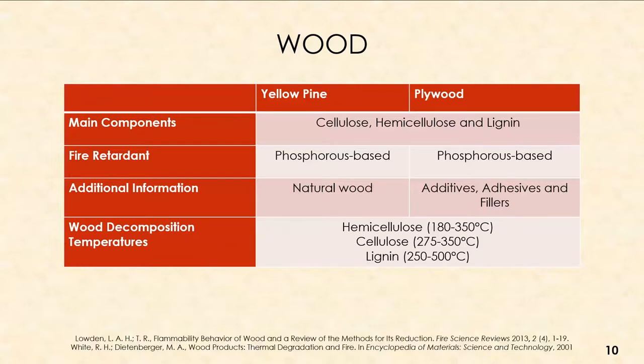For wood, I looked at yellow pine and plywood. Wood is composed of cellulose, hemicellulose, and lignin — approximately 50% cellulose and 25% each of hemicellulose and lignin. The fire retardant used is phosphorus-based. Yellow pine is a more natural wood, while plywood is man-made with additives, adhesives, and fillers. Wood undergoes a ramping-style pyrolysis: hemicellulose in the cell wall decomposes first, followed by cellulose, then lignin, based on the relative strength of those materials.